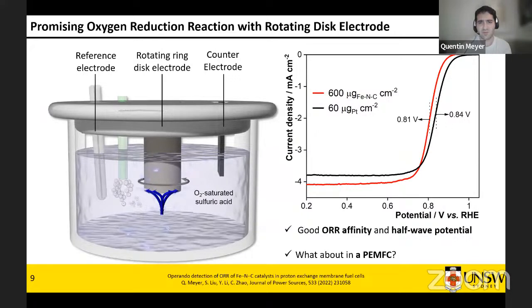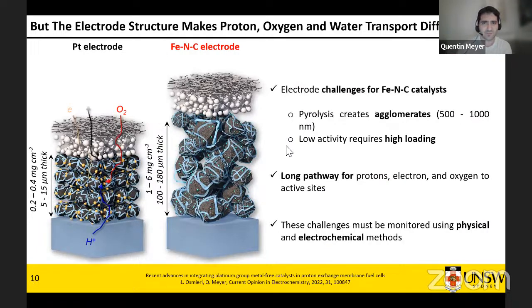Then you want to know what's happening in the fuel cell. The one thing you can notice here is we use 60 micrograms of platinum and 600 of iron-carbon. So quite a difference here, and I'll get back to this later. As I was saying, in the fuel cell, it becomes a very different environment. The reason is your iron-carbon catalyst is not quite as active as platinum, so you need to put a much higher volume. Platinum on carbon is the material you can see in here. Platinum are the small yellow particles, and carbon is the black particles over there. It has been optimized for about two decades.